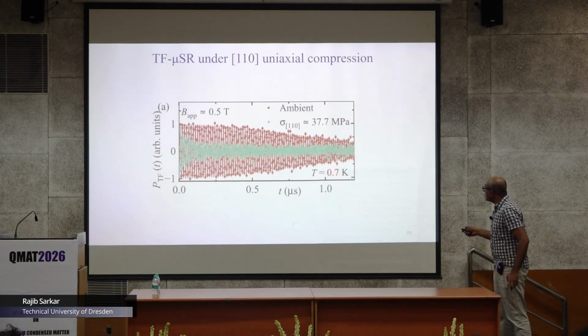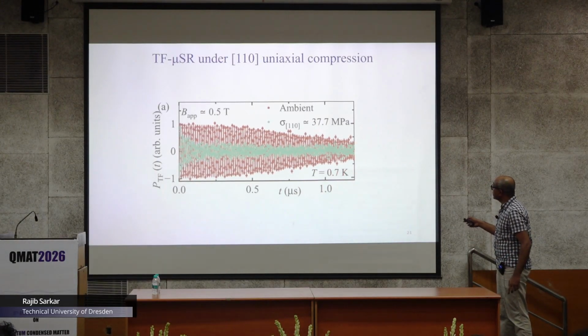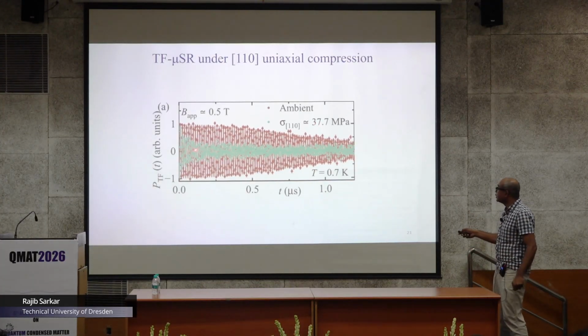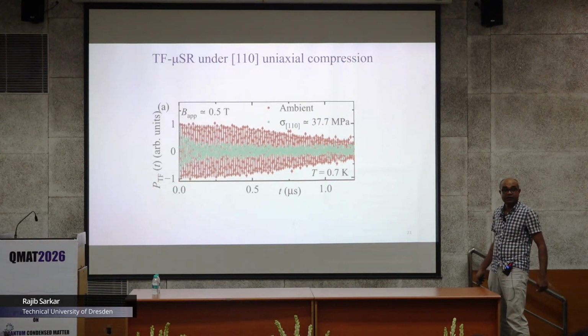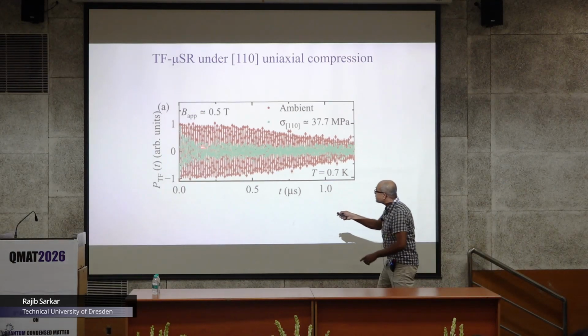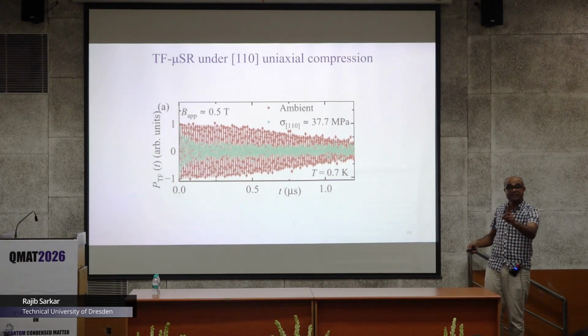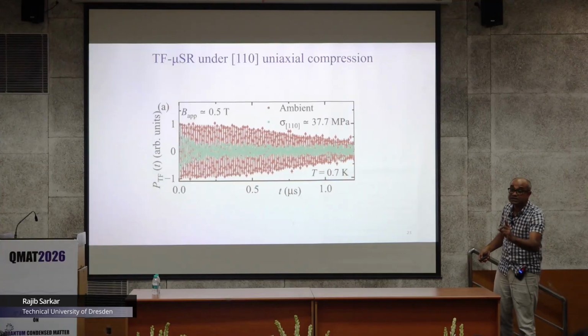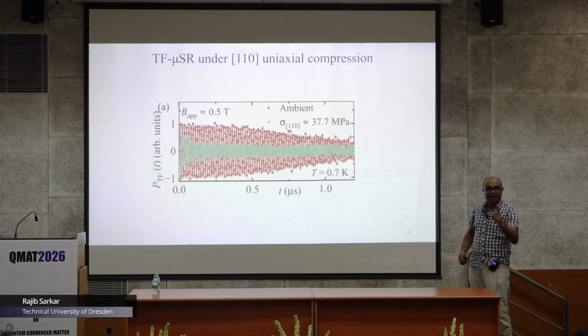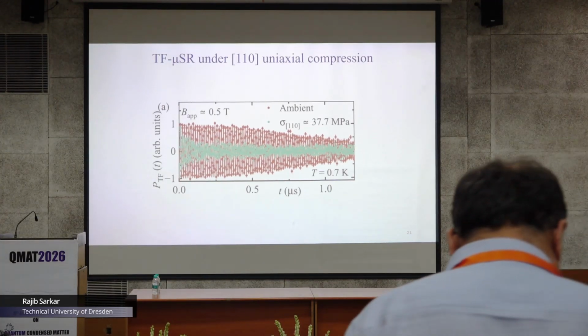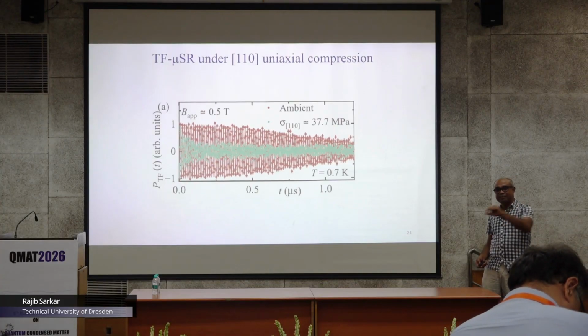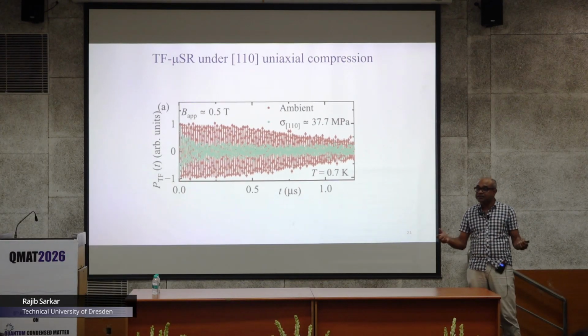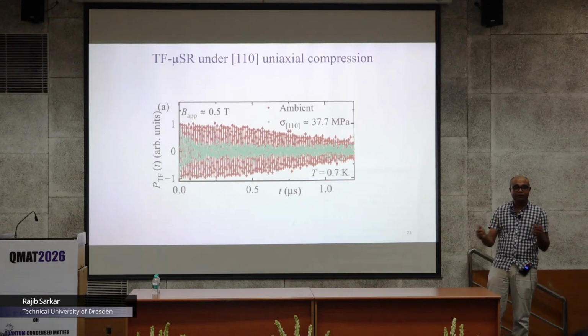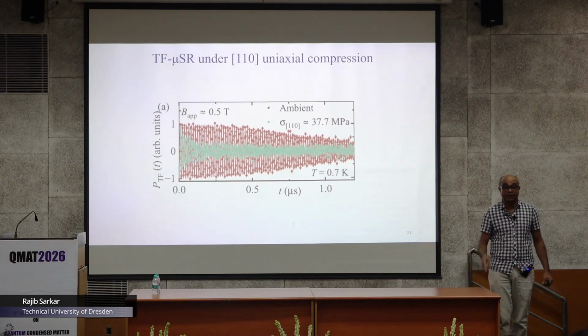Now, this whole measurement is at 0.7 Kelvin and 37 megapascal. What do you see? This is my data. We have a large amount of damping. The oscillation frequency, the resonance frequency, is the same. That means the magnitude of the internal or external field values is the same, but my damping is stronger. That essentially tells you that a very large static correlation is developing as you apply the pressure.